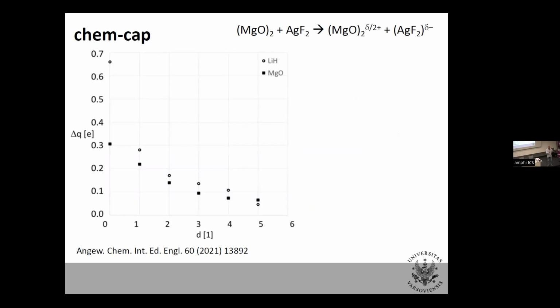And by controlling the separation, by the number of separator layers, I control charge transfer. And now I can use a stronger reducing agent, and for the same separation, I will have stronger charge transfer than for a weaker reducing agent. And it should be so, of course. But it still will not be an integer value. So I have a new tool to control charge transfer, and in this way to control properties of these layers, of one and the other. Because they have partially filled bands, and they will both be metallic now. And they were insulating before they met at some distance.